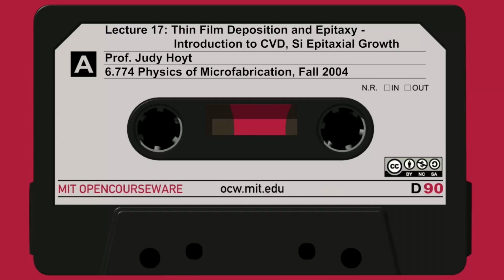That's the problem with that: whatever you're depositing on the wafers also deposits on the walls. That can give you particulate problems, because you can eventually develop so much silicon deposit on the walls that it'll start to flake, and then you get particles. So LPCVD is notorious for having particulate issues. That's kind of a basic characteristic of an LPCVD reactor.